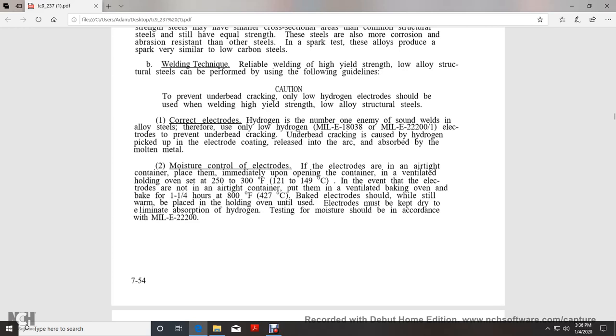If the electrodes are in an airtight container, place them immediately, on opening the container, in a ventilated holding oven set at 250 to 300 degrees Fahrenheit. If the electrodes are not in an airtight container, then in a ventilated baking oven, bake for no more than 1.25 hours at 800 degrees Fahrenheit. Baked electrodes will be placed in a holding oven until used. Electrodes shall be kept dry to eliminate absorption of hydrogen. Testing the moisture shall be in accordance with MIL-E-22200